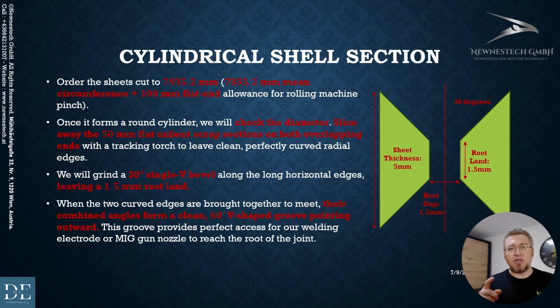So what we will do is first cut one piece of the sheet up to a length close to 8,000 millimeter. Let's say exactly 7,935.2 millimeter. This can be done by a plasma cutting system, or a CNC cutting system, or any simple torch. Why are we considering extra length, close to 100 millimeter? Because after rolling we will end up with flat ends on both sides. These flat ends are areas of close to 50 millimeters on each side, that we will cut and drop after finishing the rolling to have a perfect diameter and curve in the meeting surfaces or the edges of the cylinder. So for this, we are considering 50 millimeters, as I mentioned.